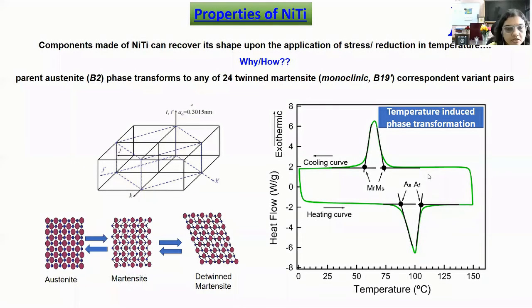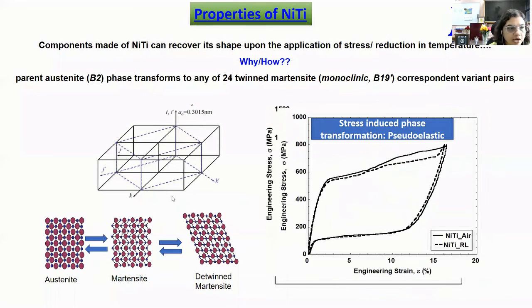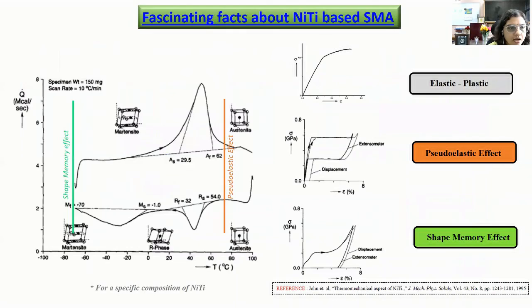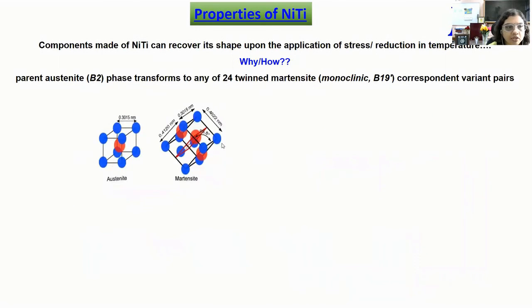Dhananjay. Okay. This is a very interesting question in the sense that we are talking about reversible deformation. Whether we are applying stress or temperature, we are going from austenite to martensite and back to austenite, which is completely reversible. After the deformation is over, we do not have any trace to know whether the deformation has actually happened or not. Other than the data, just by looking at the material, we cannot say that, right? But of these two phases, austenite and martensite, one is a high symmetry phase and one is a low symmetry phase. In the case of nickel titanium, the austenite, having a cubic structure, is the high symmetry phase, whereas the monoclinic one is the low symmetry phase.